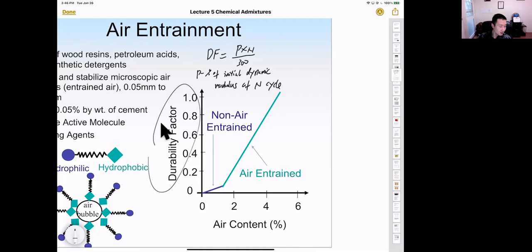So what that means is after a number of freeze-thaw cycles, we should see a reduction in modulus of elasticity of concrete. So that is the P value, the percentage of initial dynamic modulus after N freeze-thaw cycles. And N is the freeze-thaw cycles, and 300 is the reference number of freeze-thaw cycles. So the higher the durability factor, the closer the DF to 1, that means the smaller effect of freeze-thaw cycles on mechanical property of concrete. So closer to 1, the better.